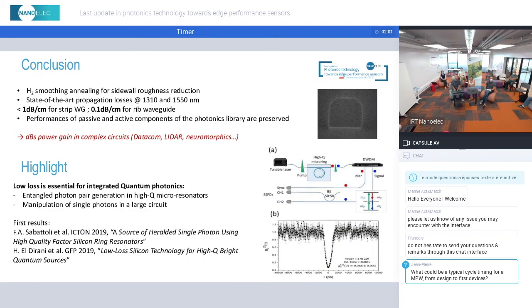Okay, so this is the conclusion. We applied this H2 smoothing annealing to reduce roughness of the waveguide. We have very good results in terms of propagation loss. We have the state of the art in terms of propagation loss at 1310 and 1550 nanometers: 1 dB per centimeter for strip and 0.1 dB per centimeter for the rib waveguide. And the components of the photonics library have the same performances with this process. We don't degrade the performance. We have several dBs of power gain in complex circuits already.